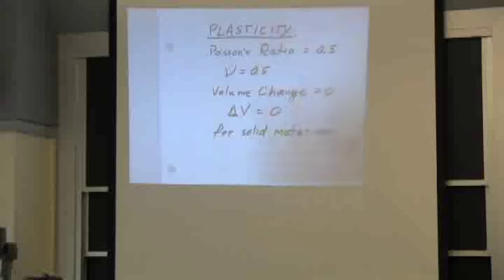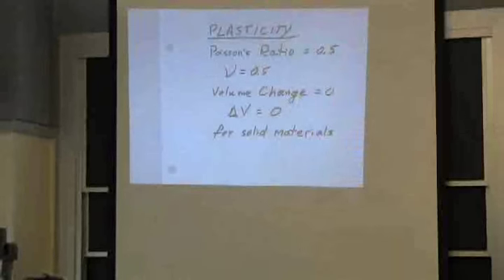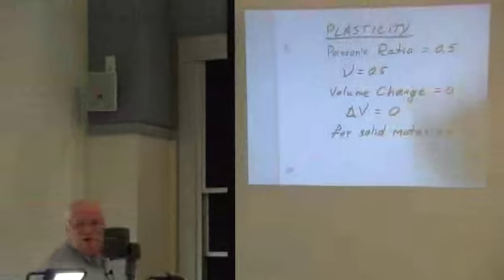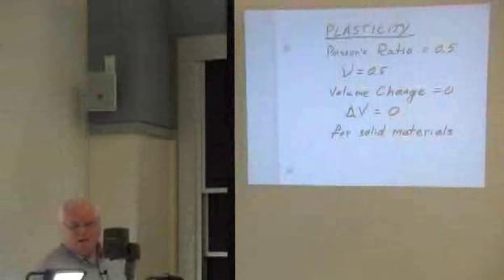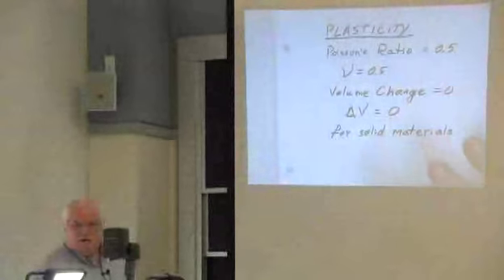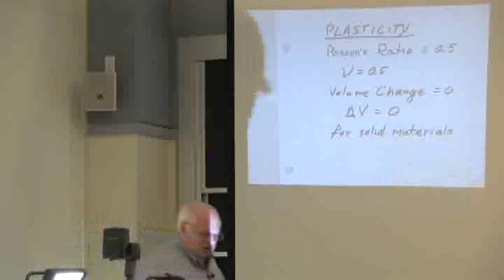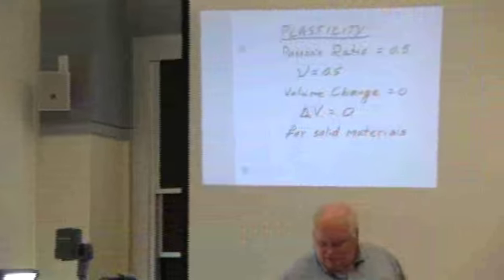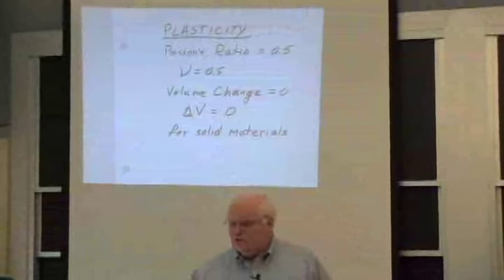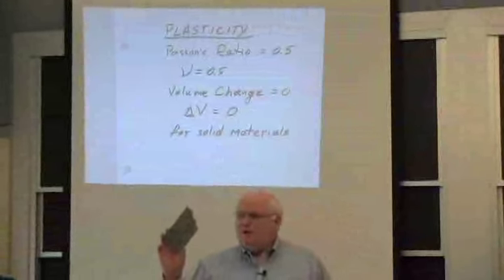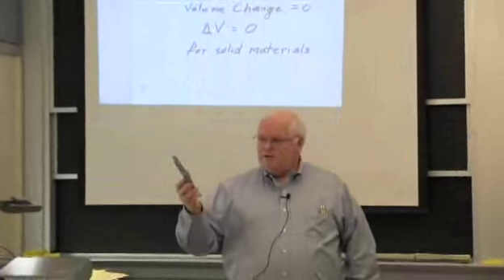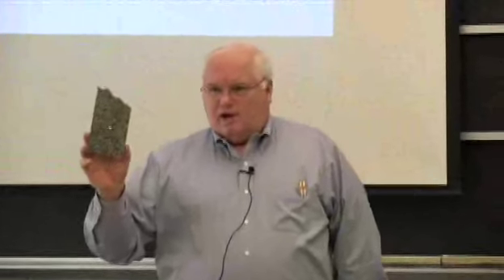So it turns out that Poisson's ratio for plasticity is a half, because there is no volume change. Okay? The material, if it's a solid material, will not change its volume. Now, if it's not a solid material, then that rule is no longer true. So here's a piece of foamed aluminum, and clearly, if I deformed this piece of foamed aluminum, it's going to have different Poisson's ratios. It's not going to have a 0 volume change if I deform it, because I'm going to break up the pores.